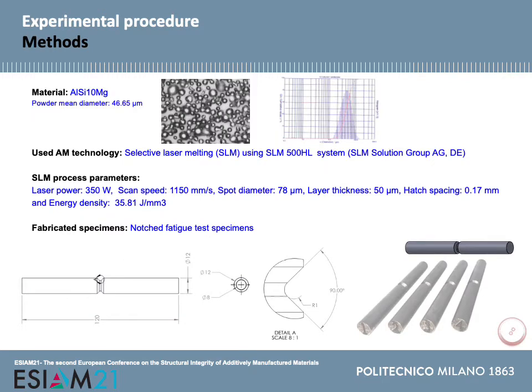Aluminium silicon 10 magnesium with powder mean diameter of 46.65 micrometer was used in this study, and also selective laser melting (SLM) as an LPBF technology was used. And here you can see the used parameters, and this is the shape and size of the fabricated notched fatigue specimens.